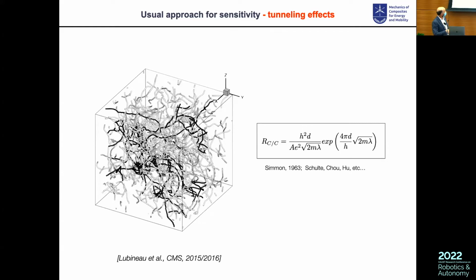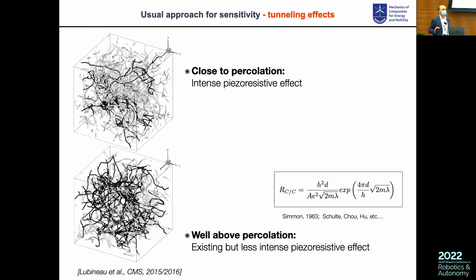Of course, this is something that has been used in all the piezo-resistive sensors that you know today. It gives a very high piezo-resistivity when you are close to percolation, because when you are close to percolation, there are very few particles touching together. So as soon as you perturb something, you increase the resistance a lot. It gives a much smaller piezo-resistivity in well-percolated networks, because you have well-established percolations and a lot of connections. So the piezo-resistivity is less intense. So this works, but clearly it doesn't give a piezo-resistive effect that is high enough.